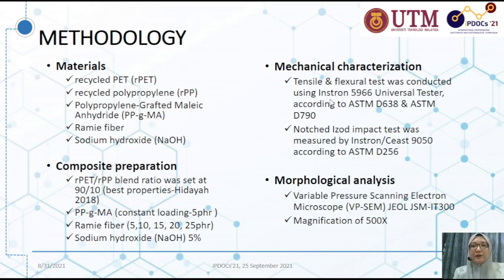For mechanical characterization, tensile and flexural tests were conducted using Instron Universal Tester according to ASTM D638 and ASTM D790. For notched Izod impact test, we use an Izod impact tester according to ASTM D256. For morphological analysis, we use a variable pressure scanning electron microscope with a magnification of 500 for each sample.